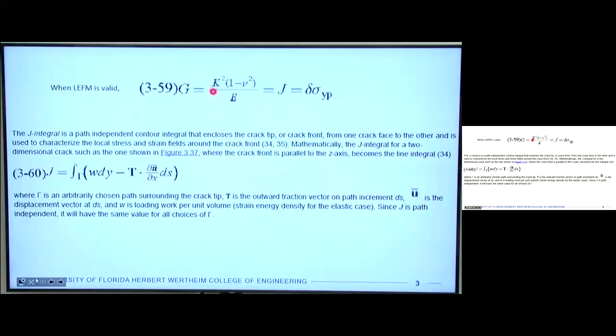K is the fracture toughness. And if we take that and square it and then multiply it times some material properties, so Poisson ratio, elastic modulus, that gives us an energy per unit area, or you can think of it as force per length, but it really is an energy per unit area. And that is going to be equal to what Griffith studied quite a bit, which is an energy release rate.